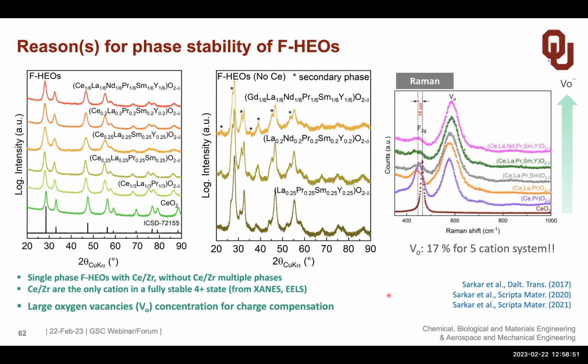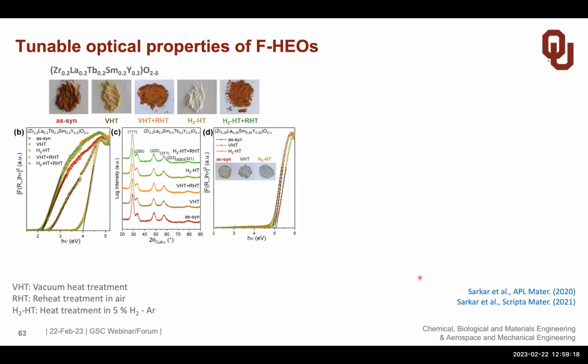What we have also shown is that we can create a lot of vacancies in the system. And this can be measured by Raman spectroscopy. Here is a pure cerium oxide, which doesn't have this particular Raman line, which is indicative of vacancies. So if we add more and more cations to the system, we have more and more oxygen vacancies in the system, which is of course also important for the properties.